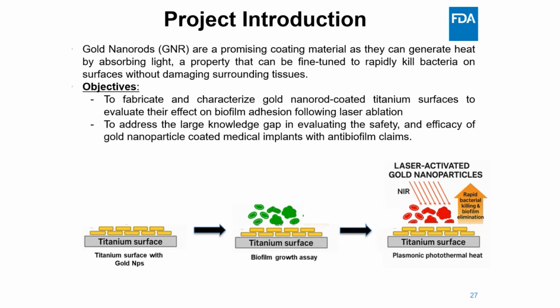These gold nanorods absorb near-infrared or NIR light through a process called localized surface plasmon resonance, where conduction electrons oscillate collectively and then relax, releasing energy as localized heat. We use NIR light because it penetrates tissue effectively and is minimally absorbed by surrounding biological components, allowing safe and targeted heating of the coated surfaces to rapidly kill bacteria without damaging the nearby tissues. Our goal is to fabricate and characterize these surfaces and evaluate their biocompatibility and antimicrobial performance, addressing the current gaps in assessing gold-based antimicrobial coatings for medical devices.